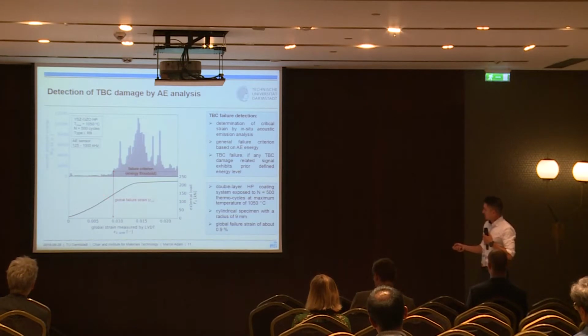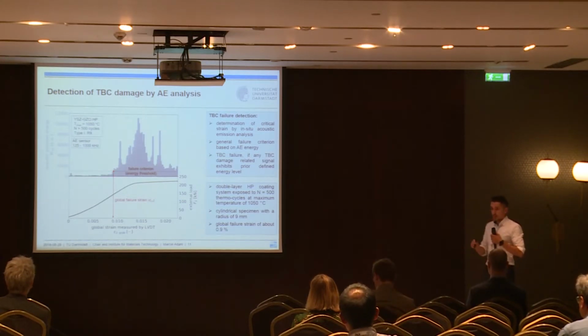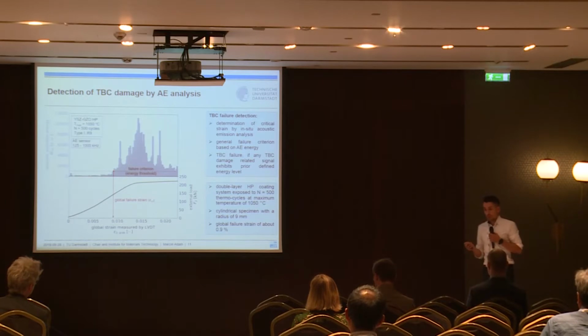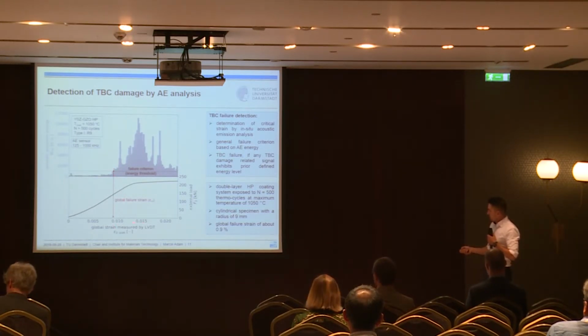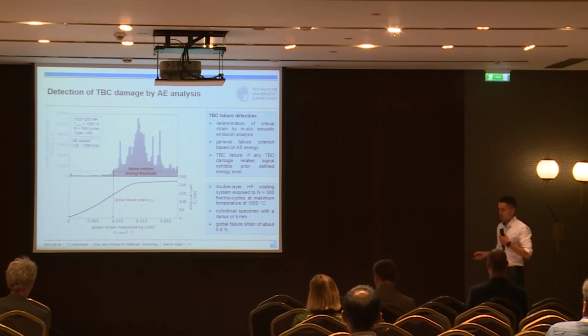And reaching a certain point of external load, there is an exponentially rising acoustic emission energy. At this point, we define this point as the critical point where the TBC is going to fail. From this point we measure the global strain, and we define this as the global failure strain of our thermal barrier coating. And in that example, we get a global failure strain of about 0.9%.